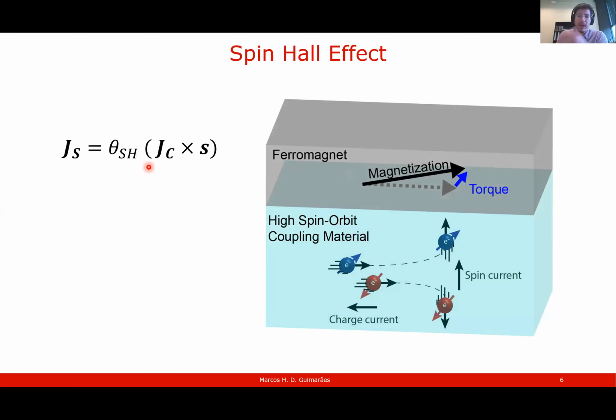And one way to create this separation of spin up and spin down is through the well-known spin Hall effect, in which you have a high spin orbit coupling material attached to a ferromagnet. If you drive a charge current, you have electrons with, let's say, spin up and spin down here. The spin up electrons are deflected to the top part of the layer. They get absorbed by the magnetic layer, and apply torque on the magnetization because of conservation of angular momentum.